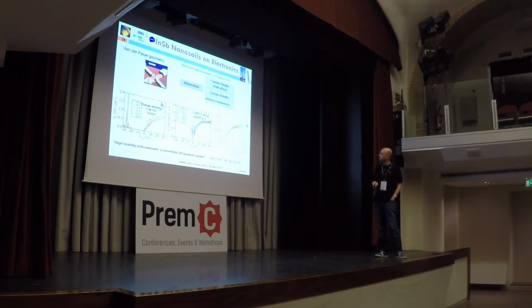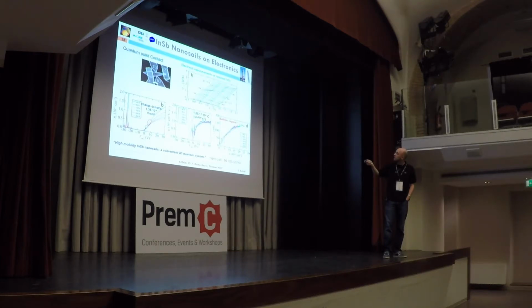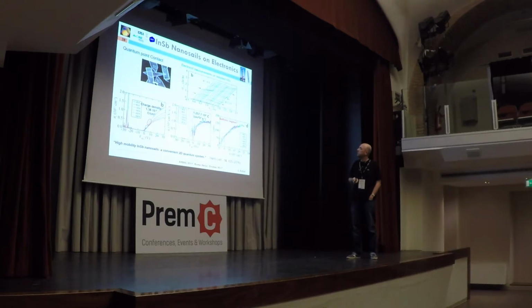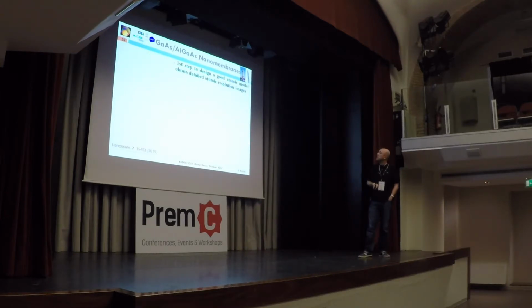So you can also check the mean free path of the electrons, and you can see that it doesn't depend on temperature. So this can mean that the scattering of these electrons is not due to the phonons. So in this case, we can have a ballistic regime, and it can be explained that you can have this perfect, let's say, quantum confinement behavior of this material. So it's perfect to have this high mobility. You can create a transistor with high mobility right here.